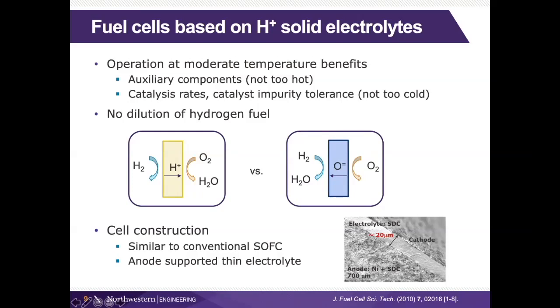In the oxygen ion conducting system, there is dilution because the oxygen ions are coming across, reacting with the protons, and we make water. So if you have a stack, then the first cell will have a high hydrogen concentration, but then as you go through the stack, you get less and less hydrogen. So the efficiency and sort of system design is not ideal. So that's one difference. On the other hand, if we're using these ceramic electrolytes, the construction is quite similar between them.